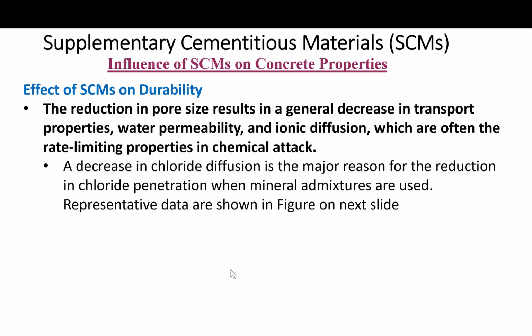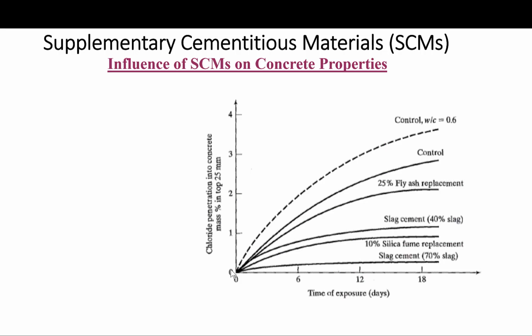A decrease in chloride diffusion is the major reason for the reduction in chloride penetration when mineral admixtures are used, as you can see in this figure showing chloride penetration into concrete mass, percent in top 25 millimeters, versus time of exposure in days.